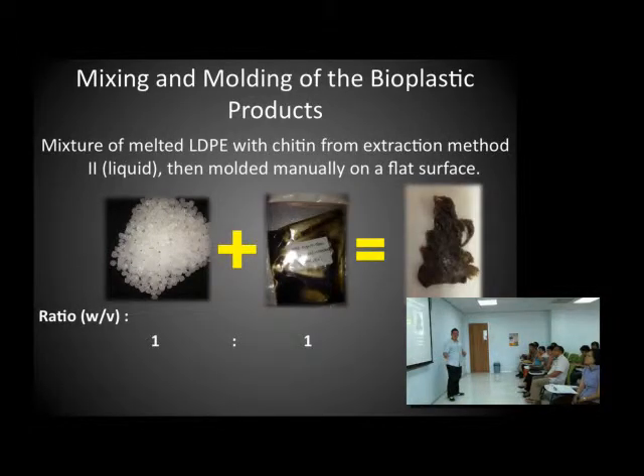And I also tried to mix the chitin extract from the second extraction method, the liquid one, with LDPE, but only with a 1:1 ratio, because as you can see the result is not very good. It has a brown color, and it actually produces brown mucus, and it has a very bad odor. Therefore, it can be concluded that this bioplastic won't qualify for further testing.